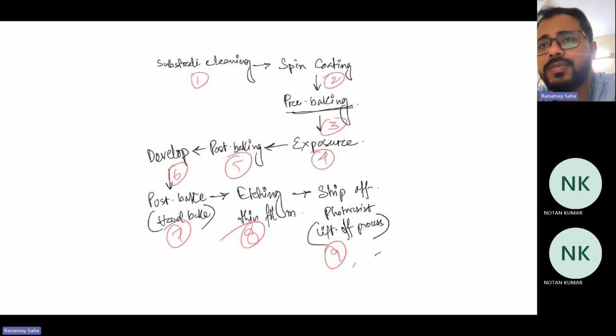And if we just look into the detailed steps, you have first substrate cleaning in order to remove any kind of dust or undesired particulate matter over the substrate surface. You clean that often with Piranha solution, and then you dry it up, maybe through compressed air or compressed nitrogen flow, and then you do the spin coating process through a spin coater. Okay, what you spin coat? You spin coat the photoresist material,